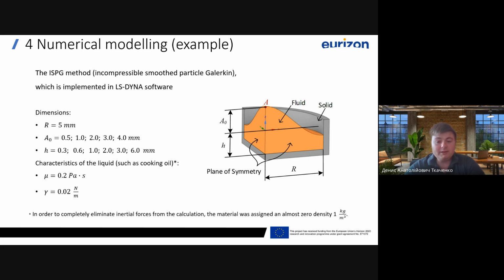To eliminate inertial effects entirely, the fluid density is set to a negligible value of 1 kilogram per cubic meter. Free slip is imposed along the vertical boundary with a 90-degree contact angle, and a no slip condition is applied at the bottom.